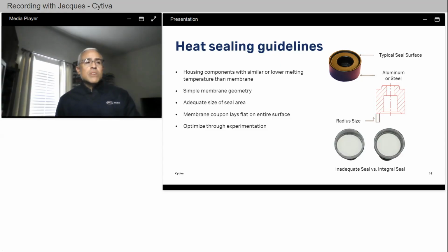Also, consider the use of a nonstick coating on the tooling to prevent the edge of the membrane coupon from sticking to the heated tool during use. And finally, the relationship between time, temperature, and pressure for your specific process must be optimized through experimentation. You may find, for example, that larger membrane devices with a corresponding large seal land may require higher pressures and temperatures than smaller devices. I'd like to point you to the image at the bottom right of the slide, which shows the difference between a inadequate seal and an integral one. A usual indicator of a good seal is transparency in the seal area, as you can see in the one to the right there. Also, the bond strength between the media and the housing surface can be evaluated by attempting to manually pull the media away from the sealing surface.